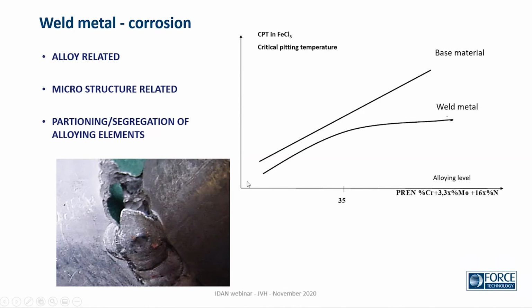So in the base material, we would see that increasing this parameter, we would increase the corrosion resistance by the CPT, the critical pitting temperature. But if we melt the material in a weld, autogenous without filler material, then we would see that it follows this line, a little below the base material. The finer the microstructure in the solidification, the faster the process, you could say, the closer these are together. And the larger the weld pool you have, the more segregation, the more they will be apart.